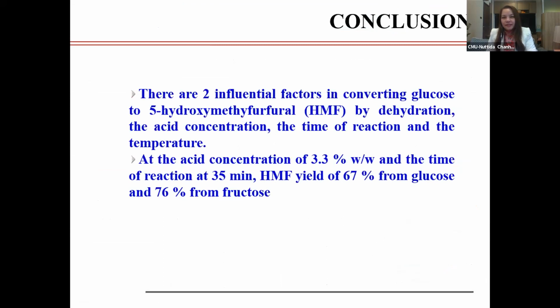In conclusion, in this research there are three factors in converting glucose to 5-hydroxymethylfurfural or HMF by dehydration: acid concentration, time and temperature. The high yield was at a concentration of 3.3% weight by weight and a time of 35 minutes, with an average yield of 67% from glucose and 76% from fructose respectively.